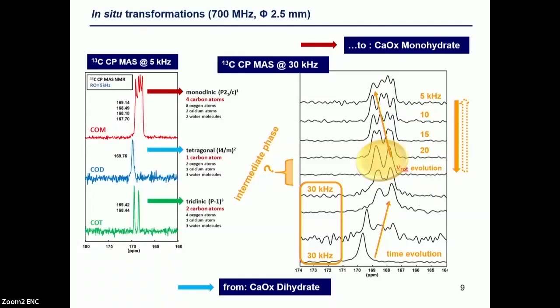So what about this intermediate phase? If you look very carefully at the literature, it was mentioned 2 times. And the attribution was the following: it should correspond to an amorphous calcium oxalate phase. And I was a little bit skeptical about this because we have clearly the distinction between peaks, and we don't have any broad peak corresponding to an amorphous sample.